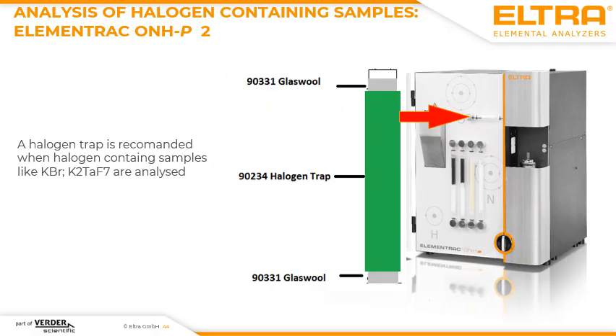Please be aware that this absorption of halogen is only suppressing the release of halogens inside the detection unit. When you are analyzing halogen-containing samples on a regular basis, you maybe would see effects on the inside of the furnace, because halogens will be released from the sample, maybe directly into the furnace. And there, in these cases, I would say a good maintenance cycle is recommended anyway.